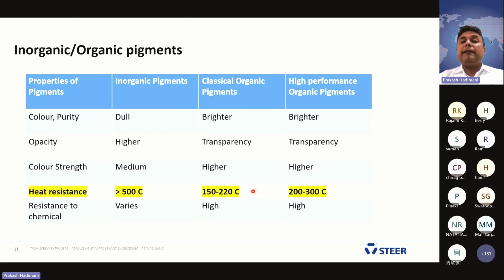We need to select the pigment depending on the requirement. When you are applying shear inside the screw, you have to select the pigments. For example, if you select the pigment of 150 to 220, like classic organic pigments, and if you are applying a higher shear rate, then it loses its property. Means you are degrading your pigments in the twin screw itself. We need to understand the behavior of the pigment, then select the pigment. Resistance to chemicals varies in the inorganic pigments and is high in the organic pigments. Most of the organic pigments are highly resistant to chemicals.